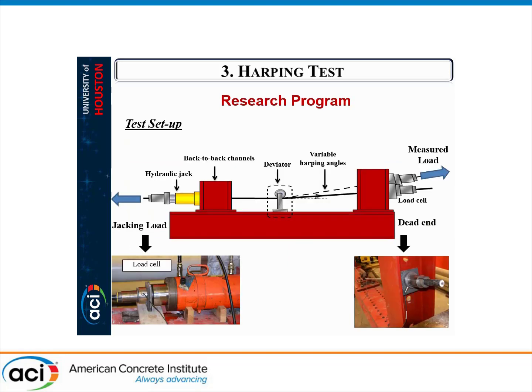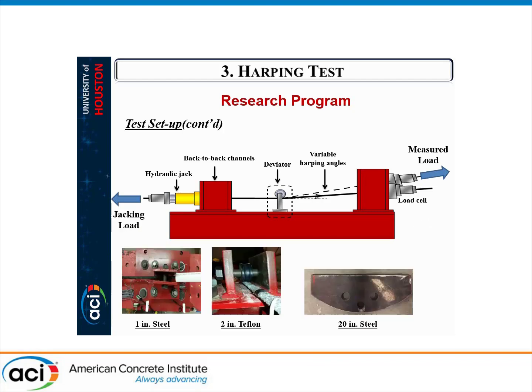The test setup is presented in this figure. We have a reaction frame, back-to-back steel channels, and steel sections at both ends. The prestressing CFRP is anchored at one end, at the dead end, and on the other side we have the hydraulic jack to apply the prestressing force, and by moving the anchor at the dead end up and down, we can obtain the desired harping angle. So we first studied the 1 inch and 2 inch, which is used for steel practice, and then we increased the harping deviator up to 20 inch diameter.